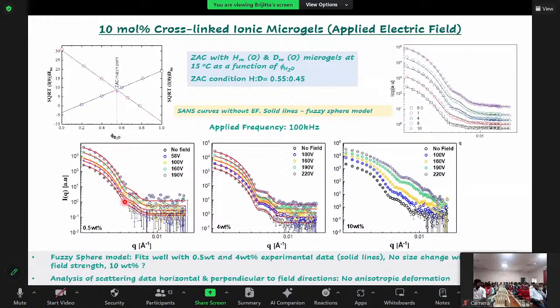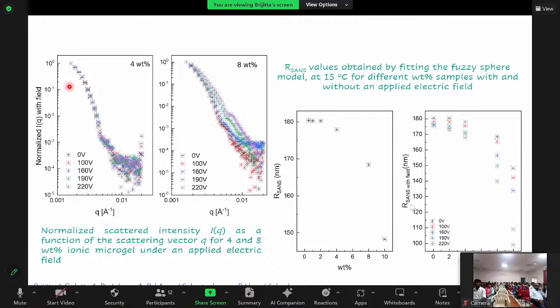When I say they don't collapse to each other, you take the field values for a given concentration and normalize them, then you see that all the data collapse into one point. Whereas when you take the field values for the higher concentration, they don't collapse. When you see a normalized scattered intensity not being collapsed in case of any scattering, that means there is some physical phenomenon happening. So in our case, there is shape change.